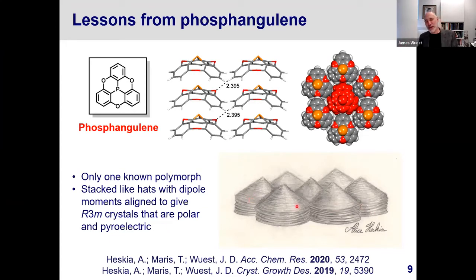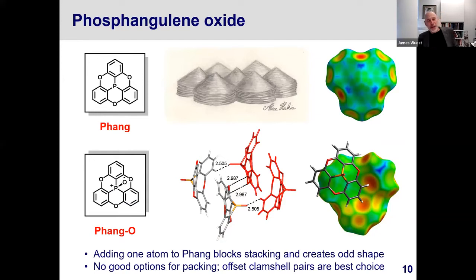Now, the curious thing about phosphangulene is that these stacks align the dipole moments, the small dipole moments of phosphangulene, and adjacent stacks align in the same way, which is not necessarily what you would expect, but it appears to be a consequence of the formation of CHO hydrogen bonds between the stacks. At any rate, this produces crystals that are, excuse me, in the R3M space group, and they're polar and pyroelectric.